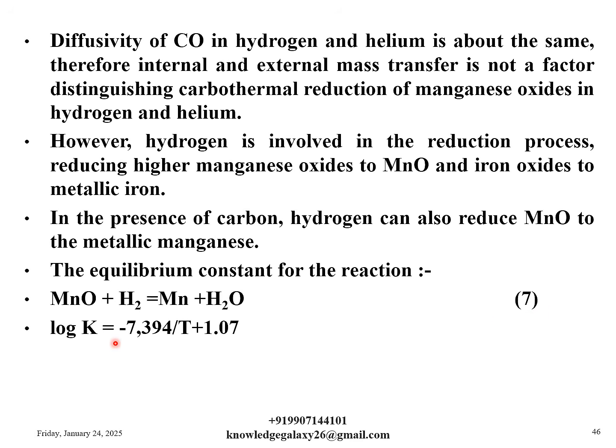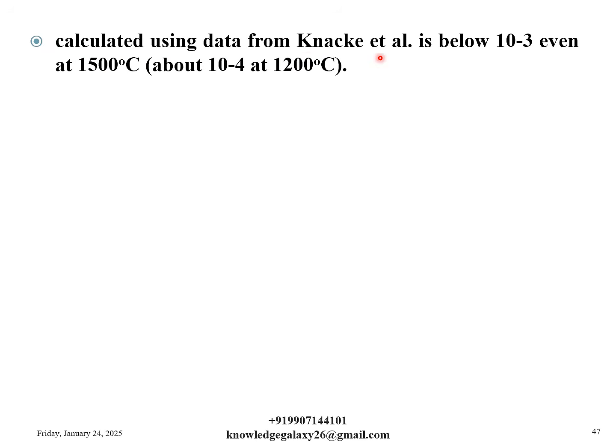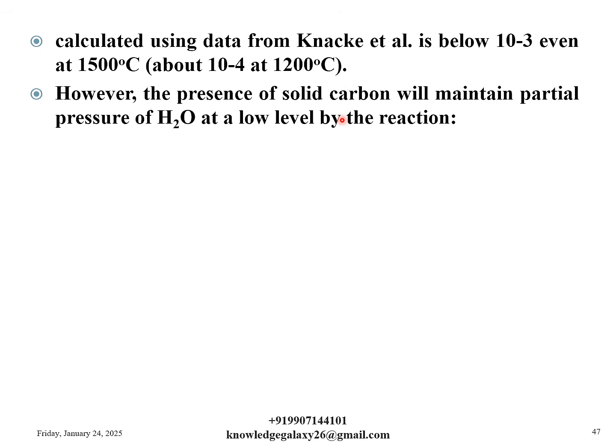And here log K is equal to minus 7394 divided by T plus 1.07, and it is calculated using data from Knacke et al. K is below 10 to the power minus 3 even at 1500 degrees Celsius, and it is about 10 to the power minus 4 at 1200 degrees Celsius. However, the presence of solid carbon will maintain partial pressure of H2O at a low level by the reaction C plus H2O gives CO plus H2. This is the equation number 8. Log K is equal to 2.68 at 1200 degrees Celsius and log K is equal to 3.48 at 1500 degrees Celsius. What makes the reduction of manganese oxide by hydrogen in the presence of solid carbon feasible?